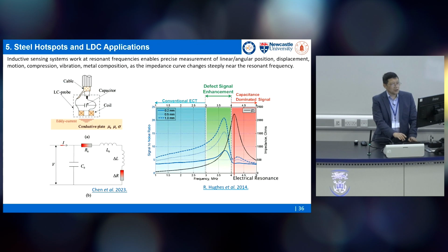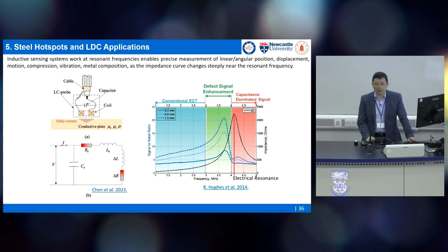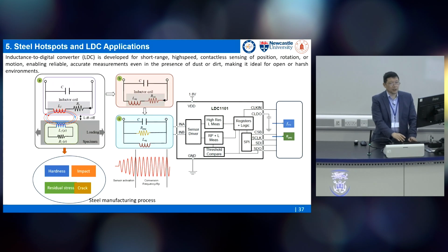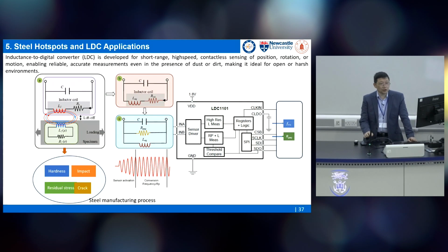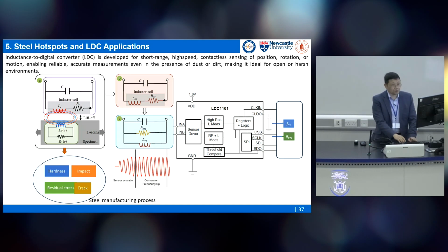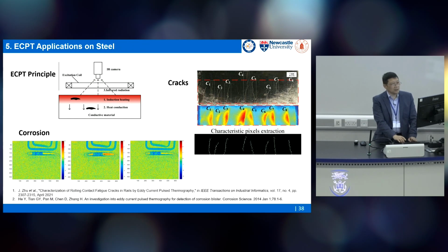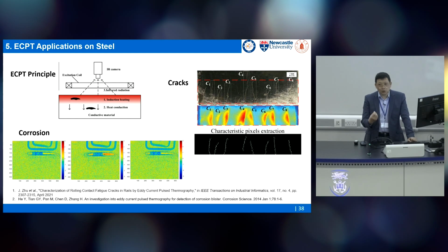inductance-to-digital converter. So what we recently do is use this kind of chip device to develop a displacement sensor. Basically measuring the gap between the sensor and the steel sample, and also measuring the defect combined together. In this way, we can get multiple functions, but overall the approach just uses one LDC device to do the job. So this is one application. Another one, rather than using a magnetic sensor, we also use eddy current to heat the sample, to measure the thermography, to measure the eddy current distribution for different applications.